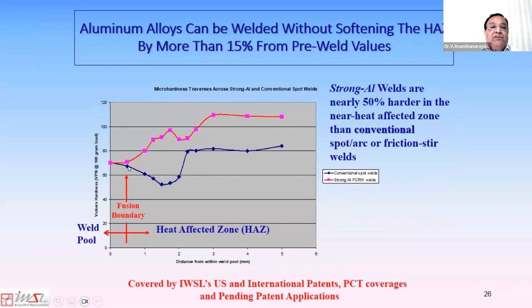And as you come into the heat affected zone from the fusion boundary, the hardness dips very much. If the parent metal hardness was about 110 Vickers, the hardness dips to something like 50 Vickers. That is more than 50% loss in hardness and strength in the heat affected zone. That makes these alloys not so serviceable in cyclic loading.